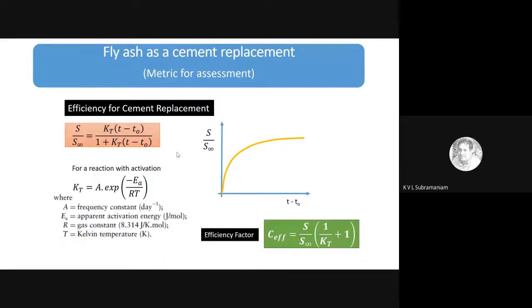Now, we developed an efficiency factor for optimizing the replacement, which is a metric for replacement. The efficiency factor itself is based on an understanding of the Arrhenius type reaction. But just to give you the way the C efficiency that I've shown here works, to develop an optimal replacement, the idea would be to achieve the same strength as what I would without using the fly ash. And we just saw in the previous example that if I do only 20% replacement of cement